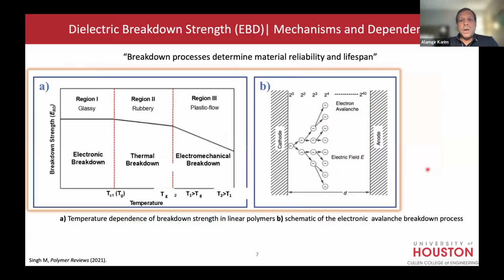So what are the mechanisms? They're different. This is already a very old slide. It is not entirely accurate, I would say, but generally in glassy polymers, and polymers well below Tg, PMMA, polystyrene at room temperature, electronic; rubbery, you can have thermal, and plastic flow. If it's well above Tg, then you can have electromechanical breakdown.